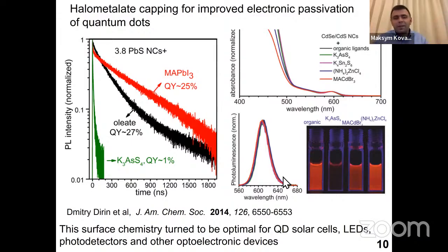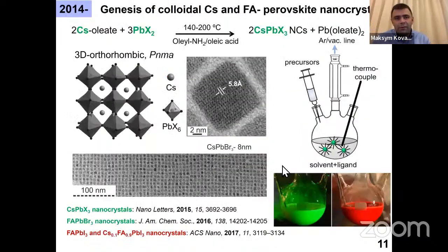And since then, we basically keep working on that because everything we do since then is super exciting, and I will share with you some of those observations. So in 2014, we began to work on a colloidal synthesis now of perovskite quantum dots. We focused initially on cesium lead halides, fully inorganic. And simply by reacting two very simple precursors in the presence of such long chain molecules, you produce nanocrystals which are cubic in shape and which are quite monodisperse. And it was easy to extend this simple synthesis to basically the entire family of these lead halide perovskites, which is formamidinium and cesium based.